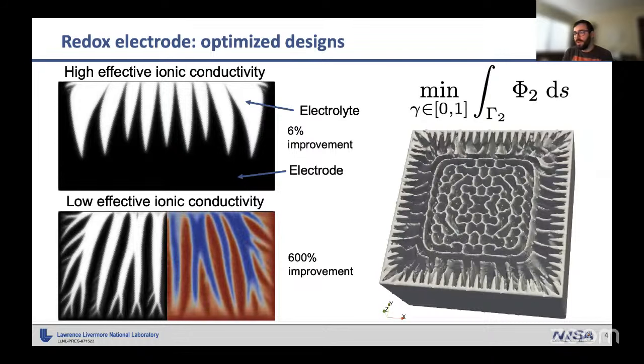So we did a sweep through different dimensionless parameters, and in this case, this is one of the, or I think maybe this one is not 6%. This may be a mistake. But you can see if you make it a high effective ionic conductivity, so if there's no trouble with ions diffusing through the electrode, then you get a small improvement, and you get these big features because you don't need small features. And if you move to this modified Brueggemann correlation with very slow ionic conductivity inside the solid, you'll start getting all sorts of, I guess, macropores that facilitate the transport, and then you get like a 6-time improvement. This is using the most extreme value we could find in the literature.